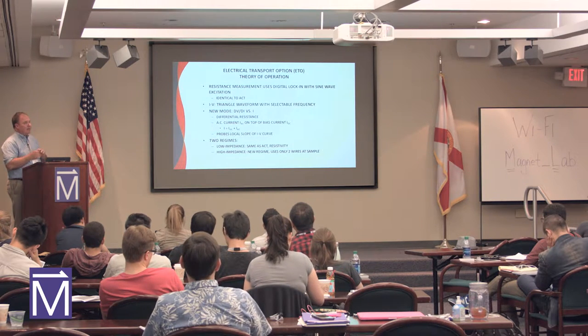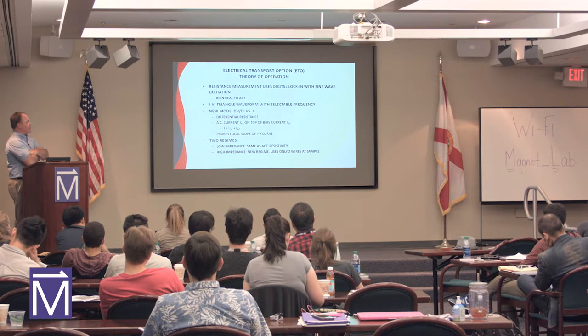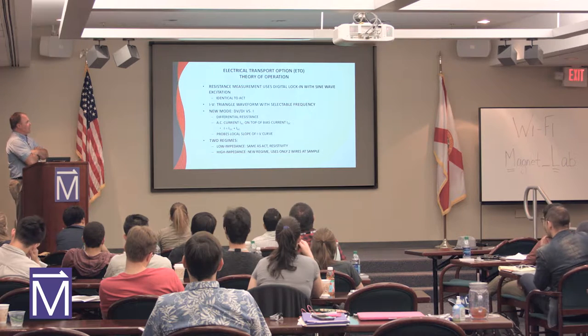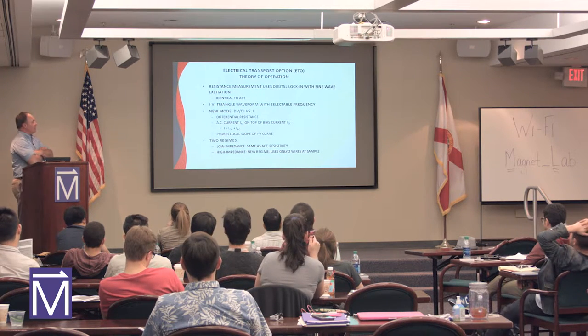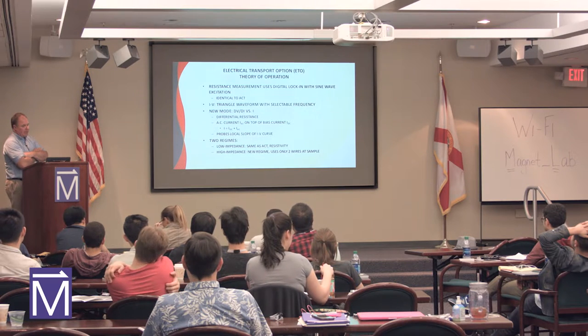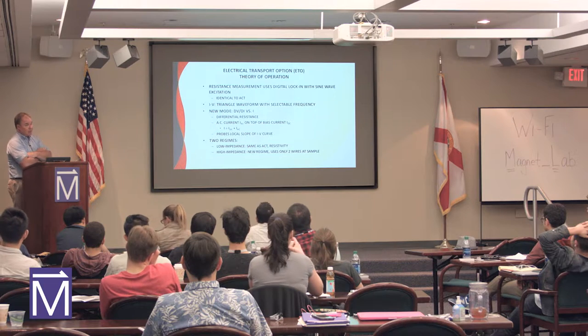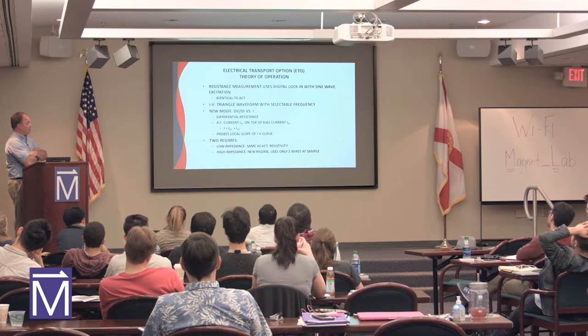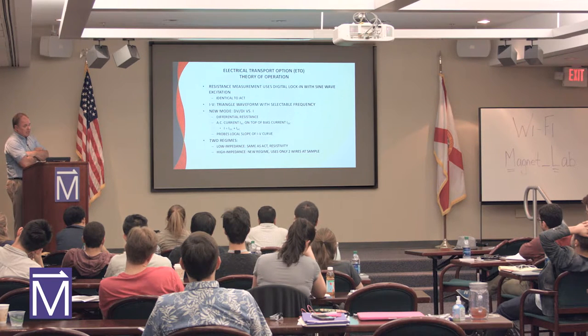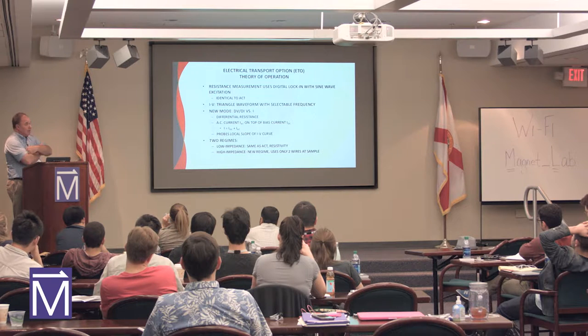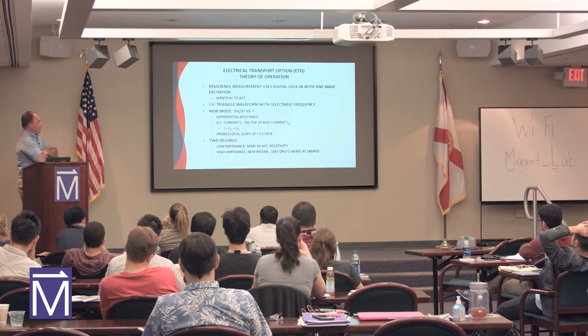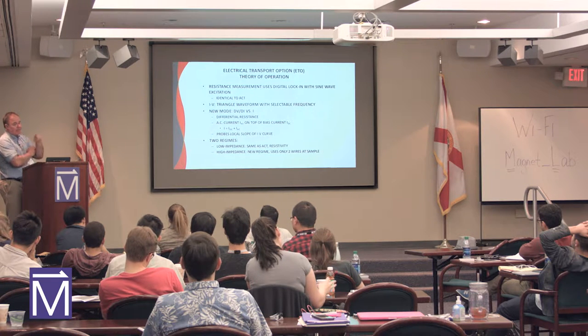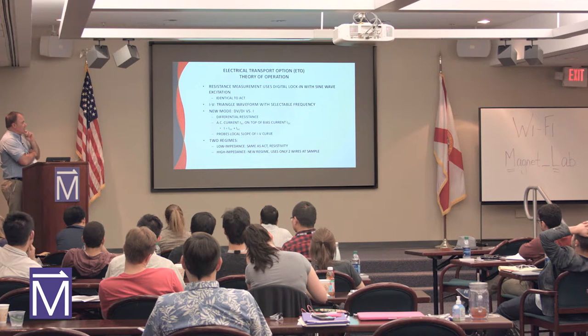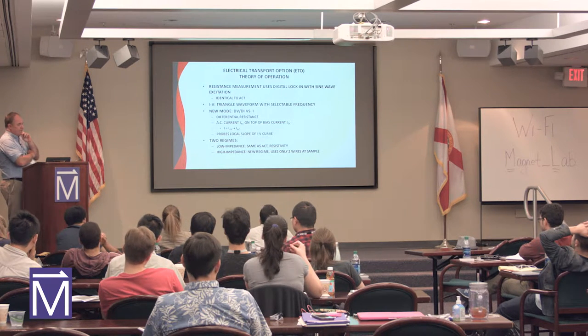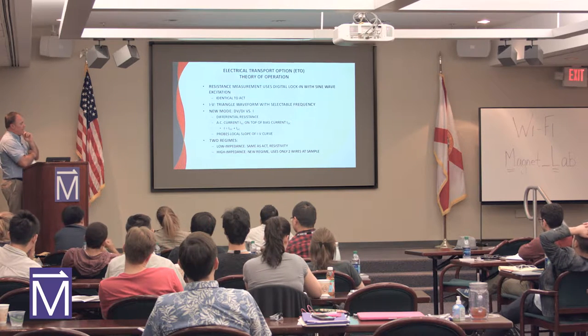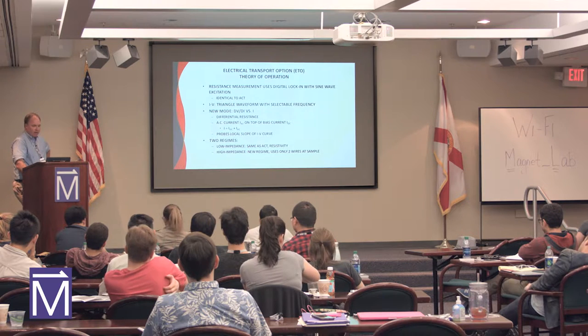We use a digital lock-in inside this, so we've got a modulated measurement technique, a lock-in technique with the DSP. It's identical to the AC transport, so you've got those features on it. You can select the waveform and the frequency for the measurement. So you've got a triangle waveform, and you can select that frequency. We've got this differential resistance mode, so you can have an AC current on top of a DC bias current. You can bias your sample with one current and then have an AC modulation on top of it. You can run it in a low impedance mode, same as the ACT in resistivity mode, and then you can run it in a high impedance measurement where you're using a two-wire type measurement.